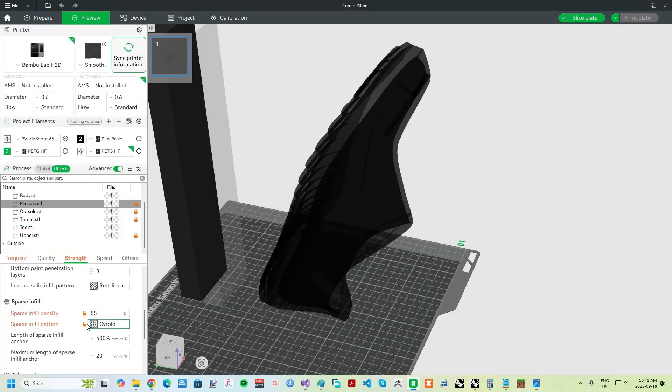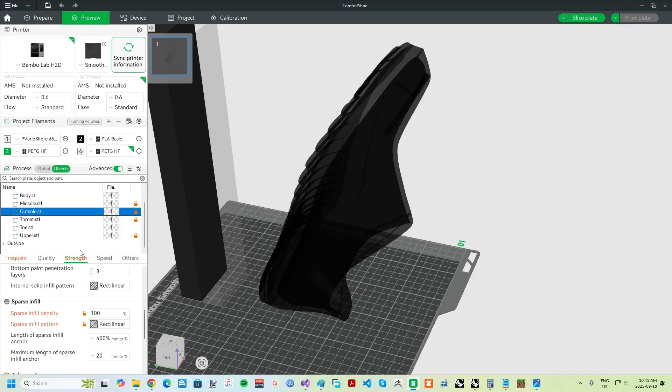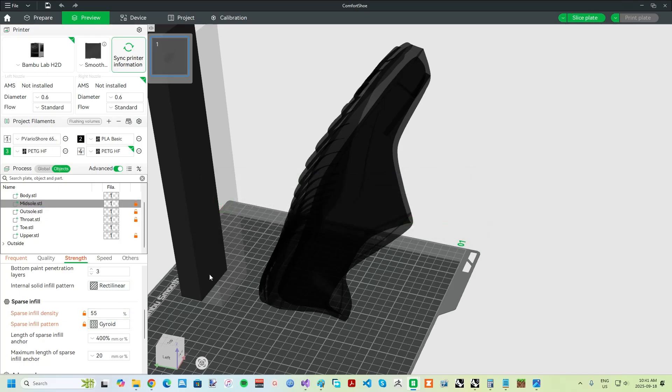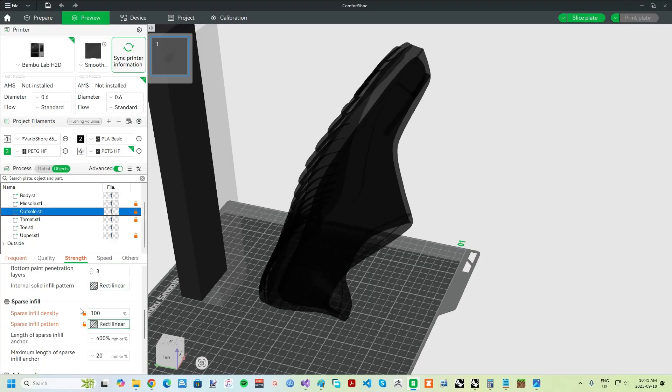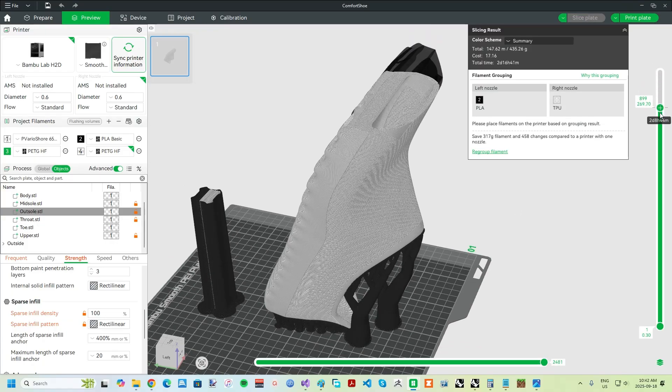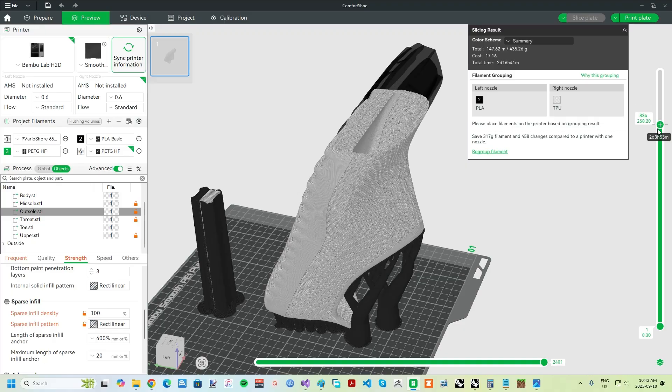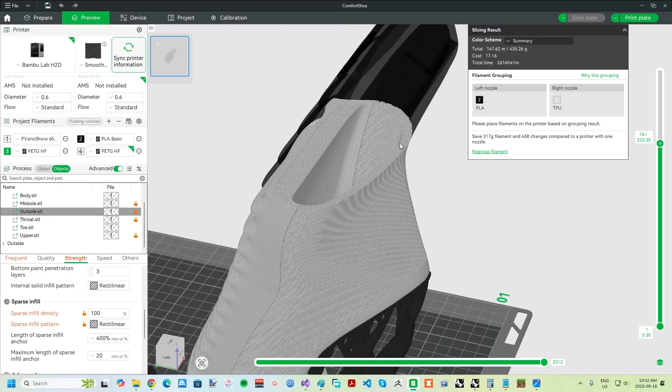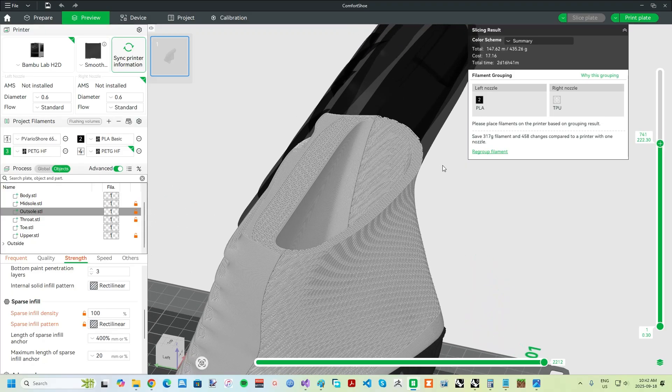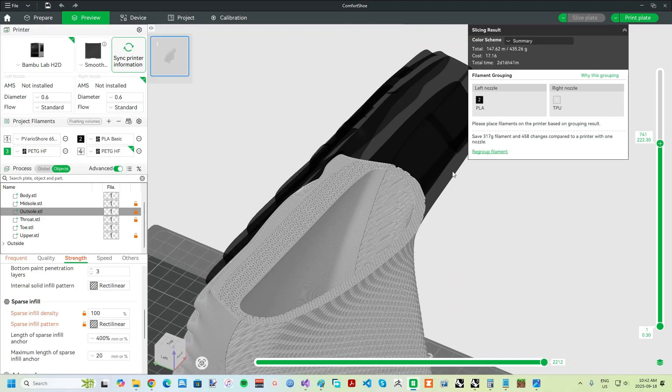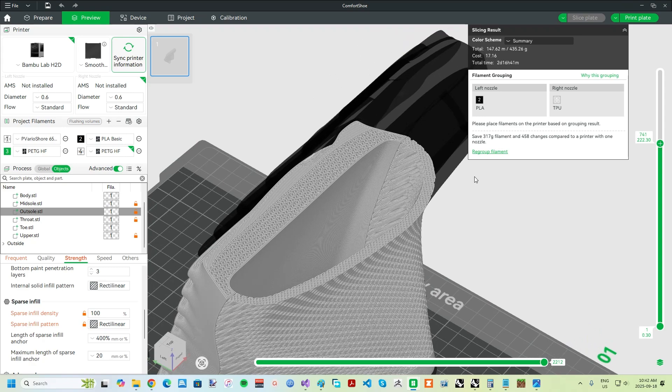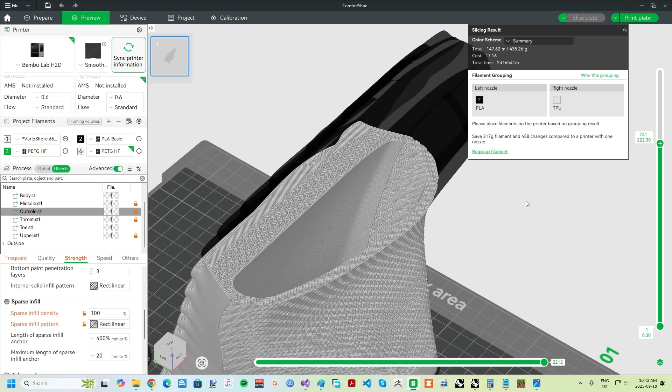Stiffness is also something that could be improved. I went with a high infill for the midsole and an entirely solid infill for the outsole. But these weren't enough to match even the notably compliant soles of the somewhat minimalist shoes I typically wear. Perhaps this could be a use case for the variable durometer capability of foaming TPU, where the nozzle temperature could be dropped in the midsole to increase the stiffness. All that being said, some people might appreciate a softer sole like this as a general purpose comfort shoe, hence my calling it that.